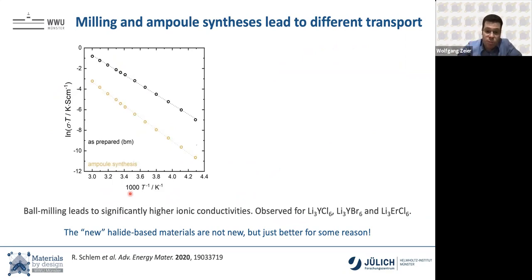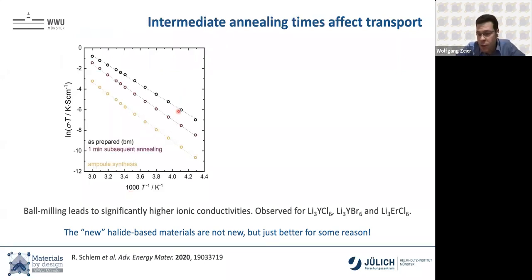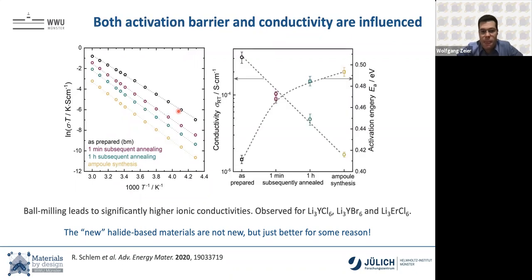And so Roman, the student that worked on this project, took a sheet out of Ajit's playbook on quenching materials. We used the ball mill sample, had it in a furnace at 550 Celsius for a minute, quenched it. Conductivity decreases. He keeps them in for an hour and quenches them. Conductivity decreases, and it comes closer to the one that we get from classic solid state synthesis. Why? Well, we actually see that the ionic conductivity, like I said, decreases, and the activation barrier increases from the ball milled, here called as prepared, to the ampule synthesis.